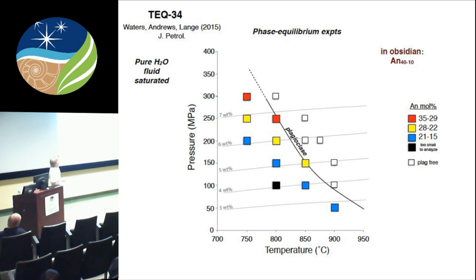All right, so now we did some phase equilibrium experiments. Laura Waters, my graduate student, is now doing a postdoc at the Smithsonian. So she led these phase equilibrium experiments on that dacite. And so what you can see is that the composition of plagioclase kind of comes at an angle with the plagioclase in curve. So the most calcic plag is here. We see up to anorthite 40. So by inference, we're inferring that 40 would probably be here. And the Fe-Ti oxides put us in this general region of the phase diagram.